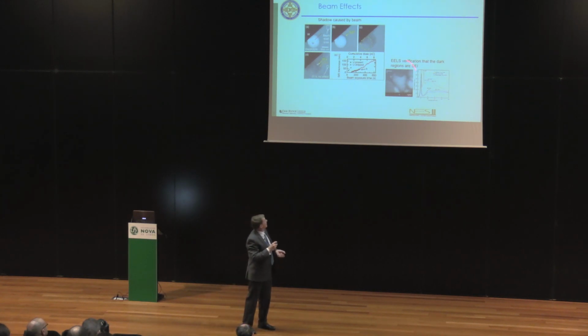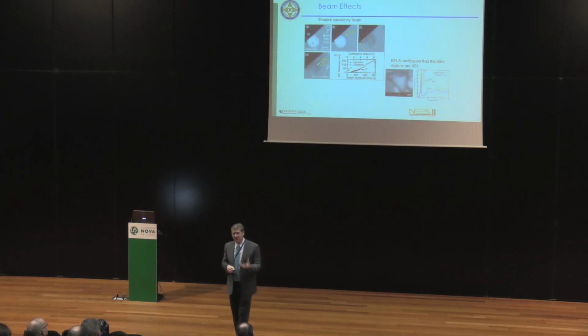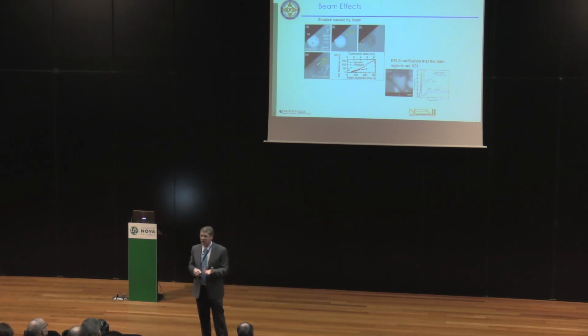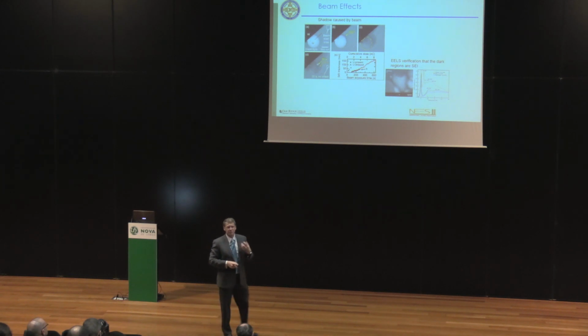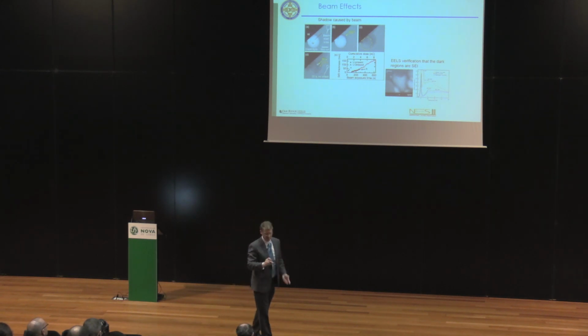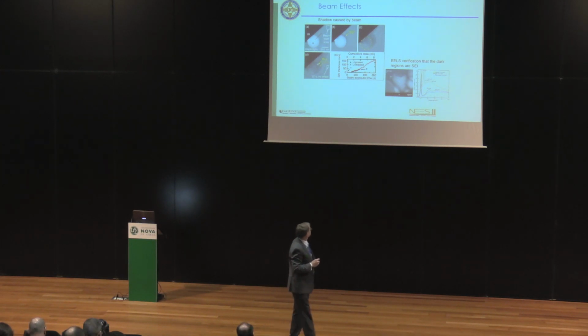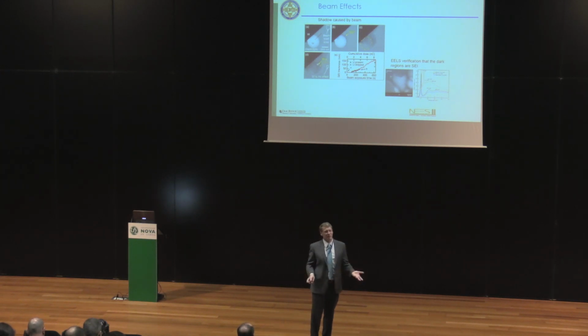So that's what they did, and they were able to demonstrate that, yes, this shell layer that's made is actually an SEI layer, so it has lithium that's locked in it, has broken down electrolyte that's locked in it, and interestingly, it forms as a shadow from where the beam was. So it's clearly charged, and it's only depositing when you're having the plating process going on. Okay, the beam is affecting it.